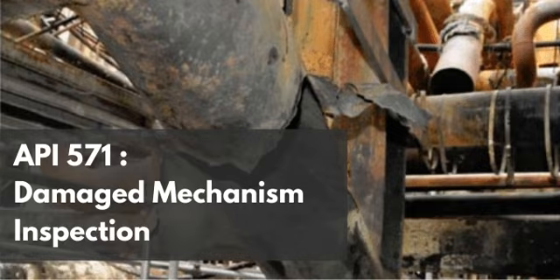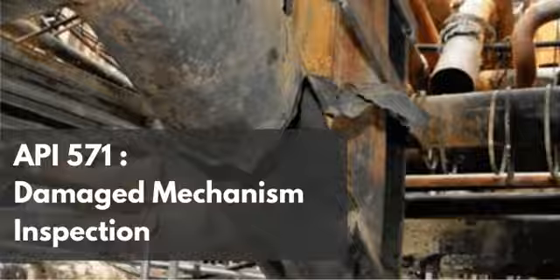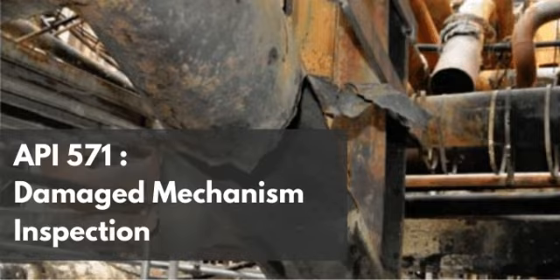What does that damage actually look like if you were to cut the pipe open and look at it? It does not look like rust, and it doesn't look like a gentle thinning. It manifests as a deeply carved, incredibly sharp canyon or groove running right along the internal circumferential weld seam. Wow. It looks like someone took a machining tool and just routed out the metal, and the severity can be staggering. Field cases frequently show this grooving going as deep as half the thickness of the material. Half the wall thickness. Eaten away, and a highly localized line, specifically at the weld, and a line carrying high-temperature, hazardous, flammable chemical. That is a ticking time bomb.